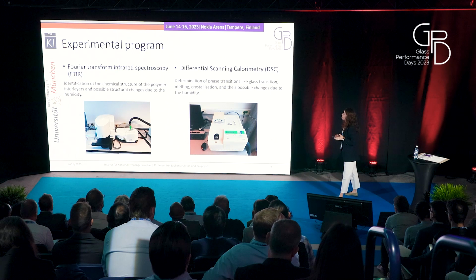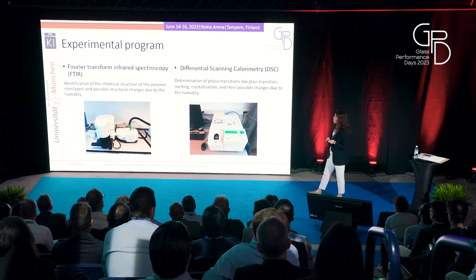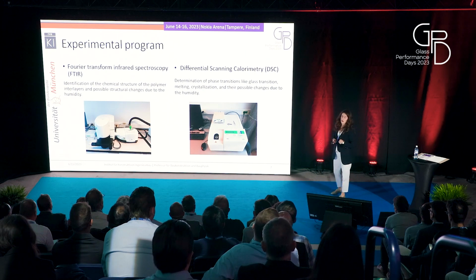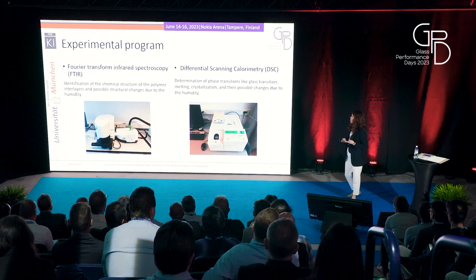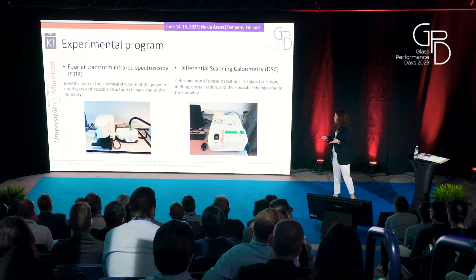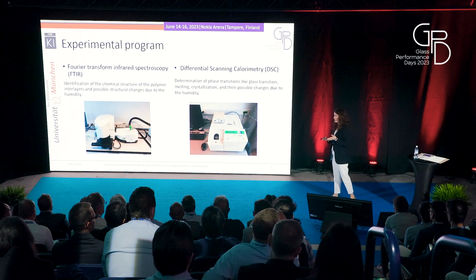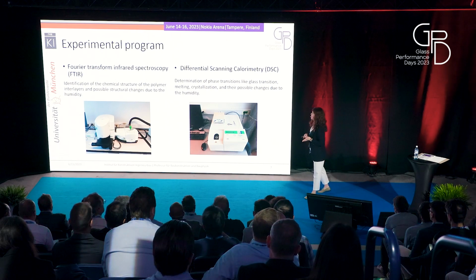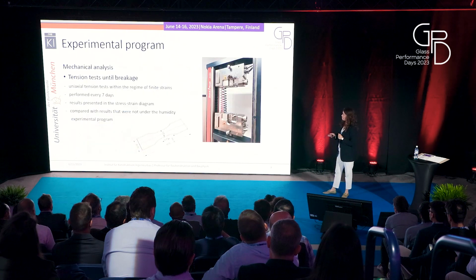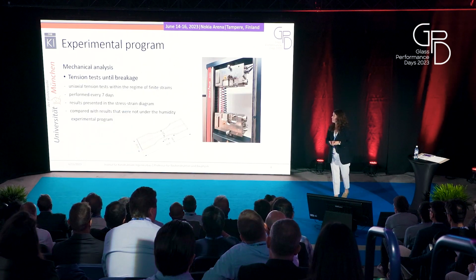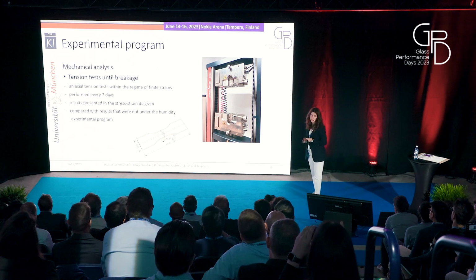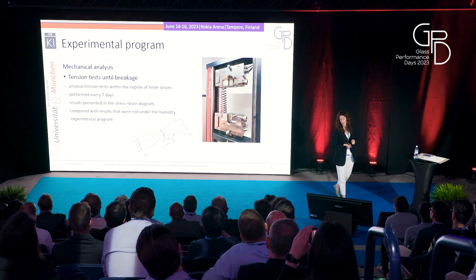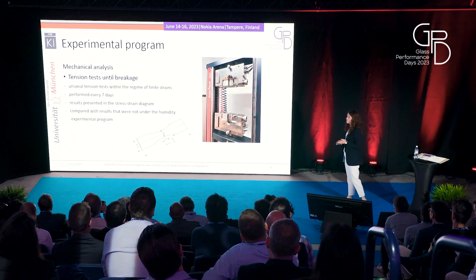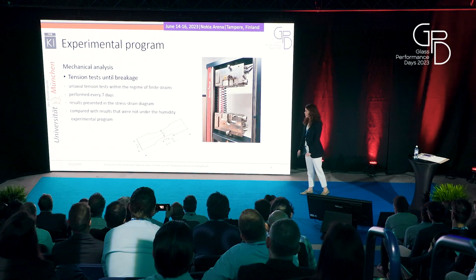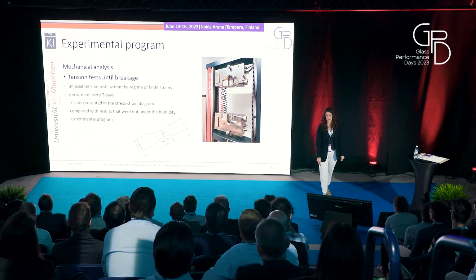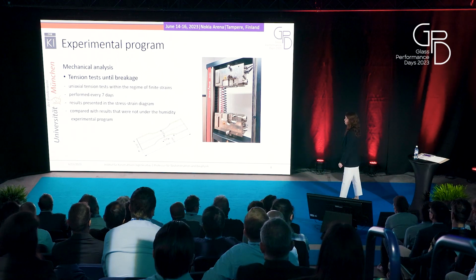Differential scanning calorimetry is used for determination of some main characteristics of the polymer, like determining the glass transition of a certain polymer, the melting phase, the crystallization phase. We did it here again to see whether there are some changes due to the humidity. And in the end, we also did the mechanical analysis, the tension test until breakage within the regime of finite strains. We performed them before, and every 7 days we presented results in a stress strain diagram, and we compared those results with those done before exposure to the humidity program.